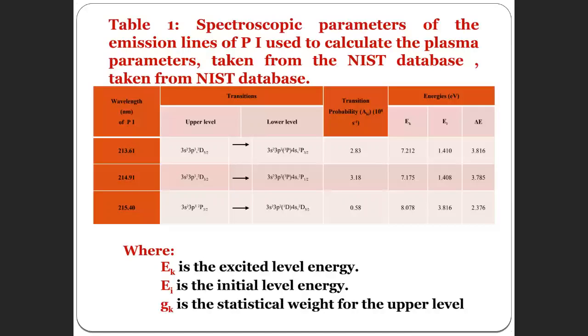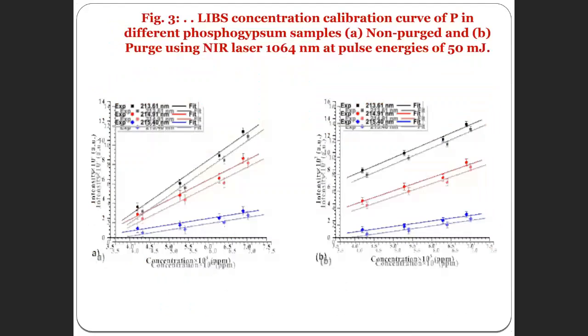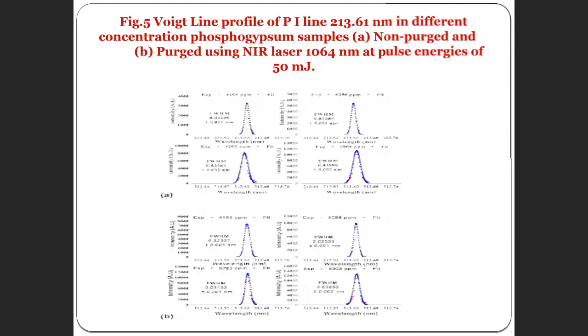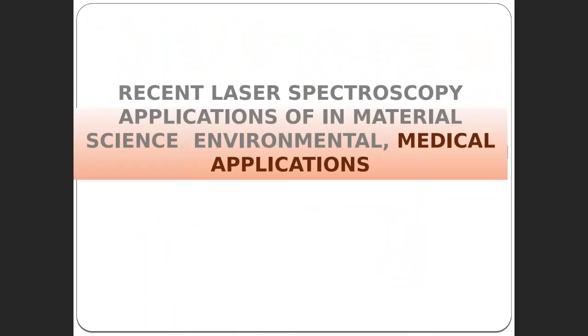So we use LIBS technique to analyze the content of this sample, and we calculate the plasma temperature and electron density, and we made calibration curves, and we calculated how much the phosphorus content in these materials.